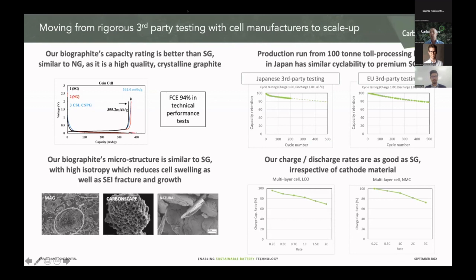And we've produced 100 tons at a rate of 100 tons per year. We will be scaling up from that 100 tons per year to 1,000 and then 10,000 tons per year, using the same equipment that we currently use, just more of it and slightly larger. Everything is from readily available equipment. And on our charge and discharge rates, we've tested with LCO, with NMC, we're currently testing with LFP chemical configuration, and we have the same performance across the piece.